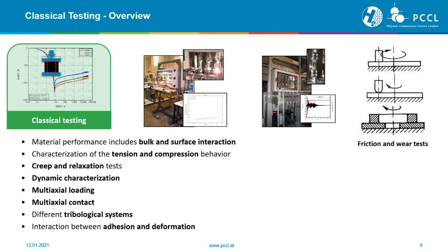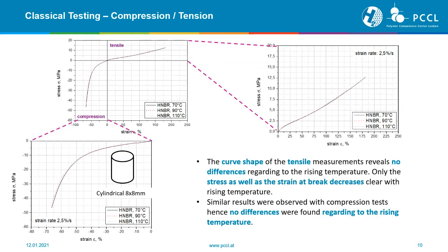The classical material characterization, as we all know, in the field of material characterization of polymers includes tension, compression tests, creep, relaxation, dynamic mechanical characterization. We can characterize multi-axial loading. We can characterize multi-axial contacts with different tribological systems and with interaction between adhesion, deformation, and all different materials and multi-layer buildups. When we think of elastomers in this field of application, a very simple example, compression tension, then you see here in the first step the compression and tension curve of an HNBR, and you see here the strong nonlinear behavior and the difference between the compression and tension behavior of the material.